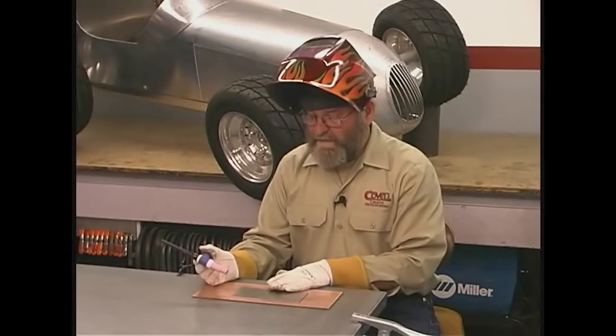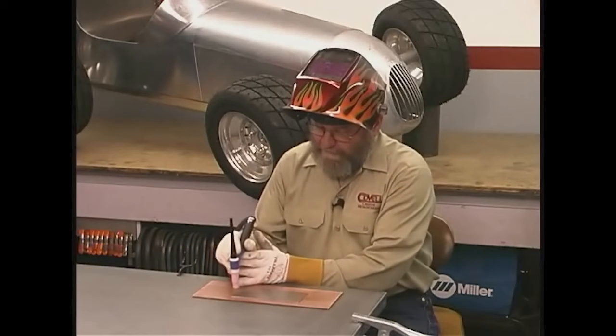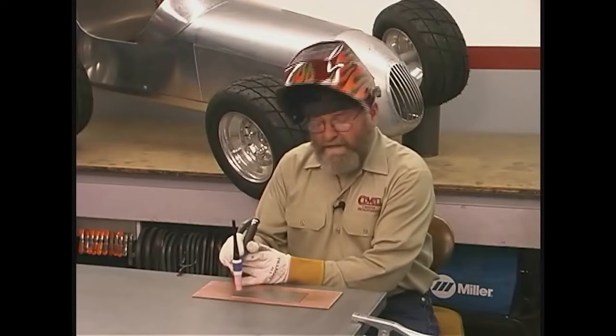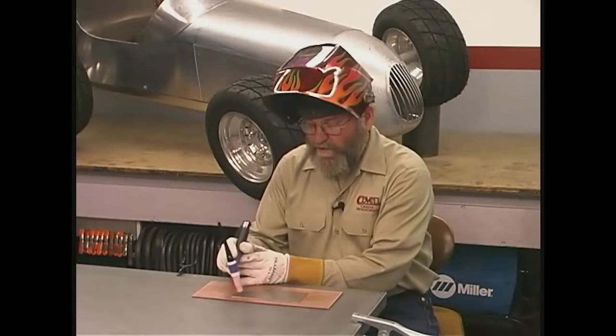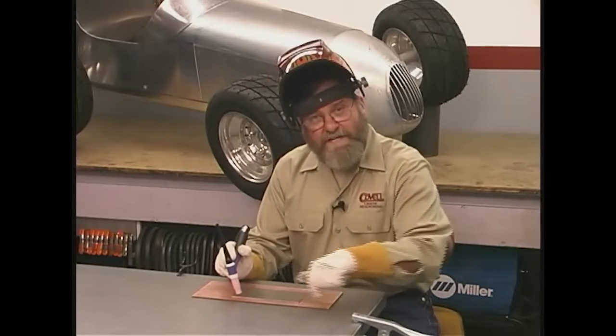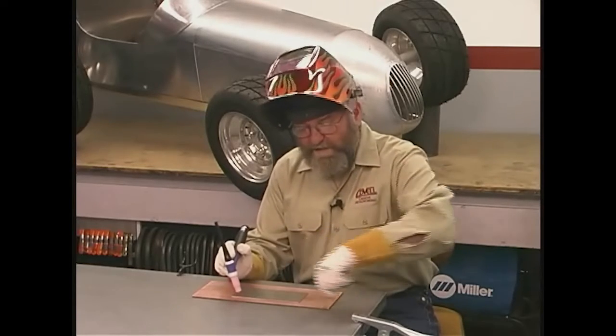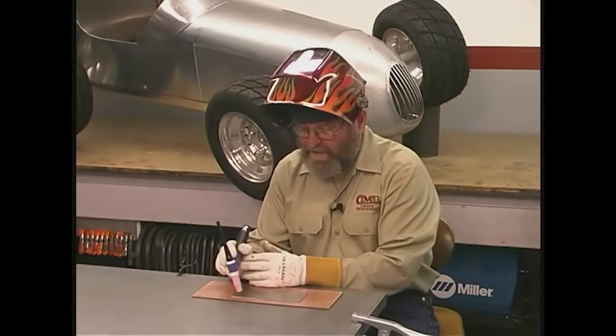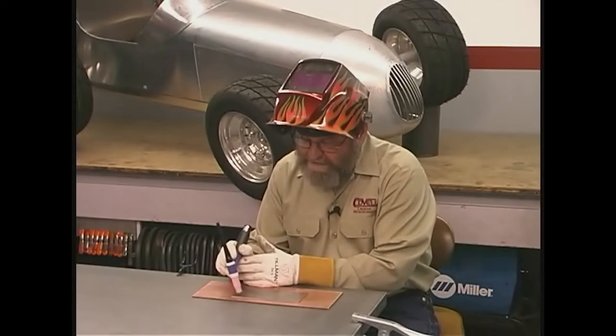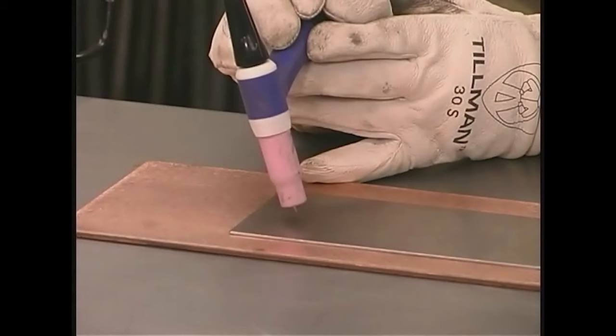So let's talk now about the torch positioning. First, hold the torch vertical and then angle it 10 or 20 degrees in the direction of travel. We're going to be moving the torch in this direction once we start welding. Then the next step is to get the proper gap between the tungsten electrode and the workpiece. It should be just about 1/16 of an inch.